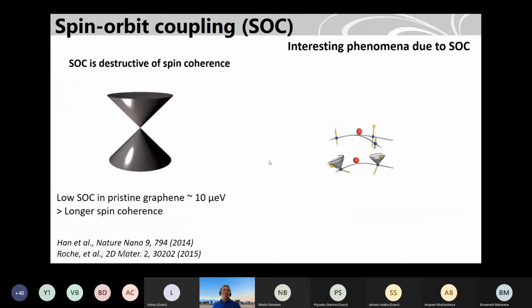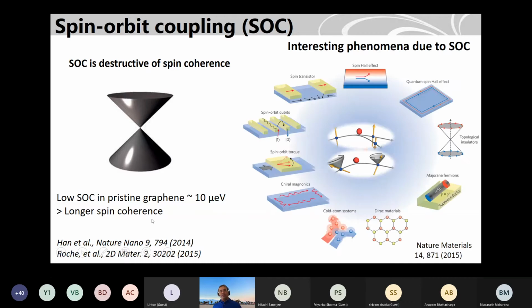So first, the spin orbit proximity. As you know, graphene has a Dirac band structure, low spin orbit coupling in pristine graphene, and it should be around 10 micro electron volt of spin orbit coupling. So that gives the long coherence length. But as you know, if you have spin orbit coupling in graphene, maybe you can explore lots of properties which have not been done with graphene. So that can be quite interesting.